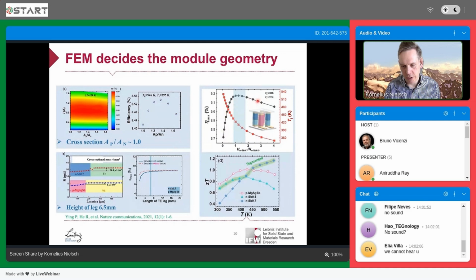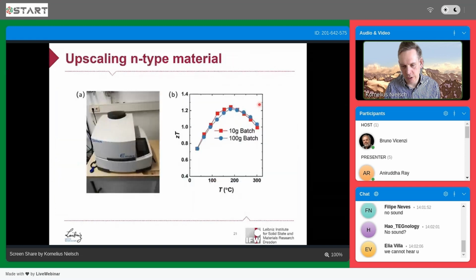We achieved about 7%. And I've also shown that we were able to further optimize the performance. One of the questions, and I think this makes a big difference, is about upscaling the synthesis. Typically we fabricate our thermoelectric material in batches of 10 grams. The goal was to go to, for example, 100 grams.